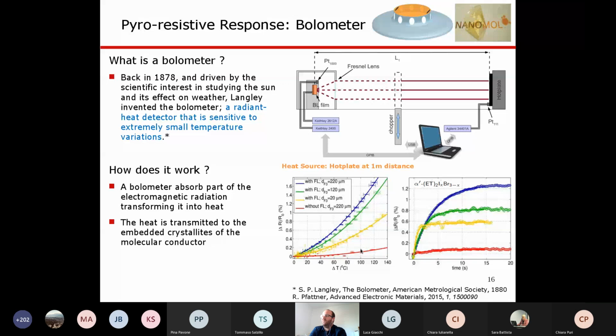And if we do so, we did different combinations of different materials and different setups. But essentially what we see is that at a higher temperature, this resistance starts to change. So we can actually, at a distance, without touching the hot plate, determine its temperature. Now, as you see here, this is around 100 degrees. Okay, so that's not very interesting. So we were thinking, okay, maybe we can try to measure something else.